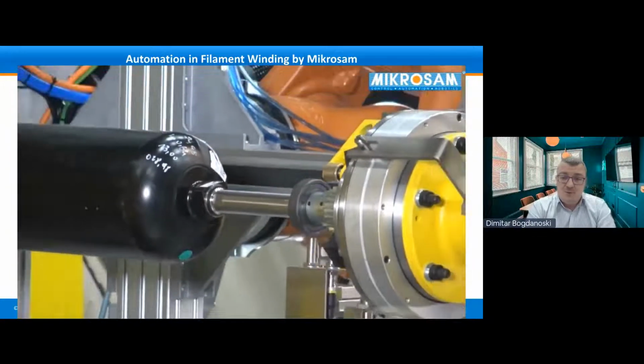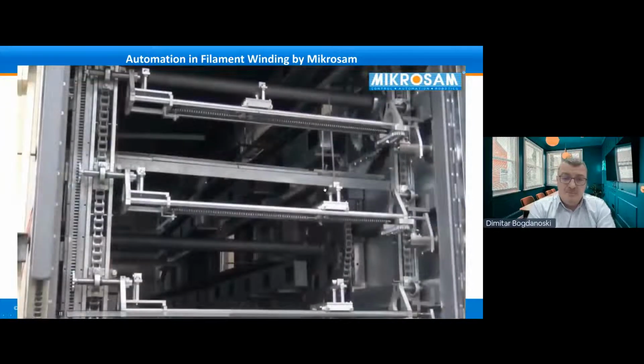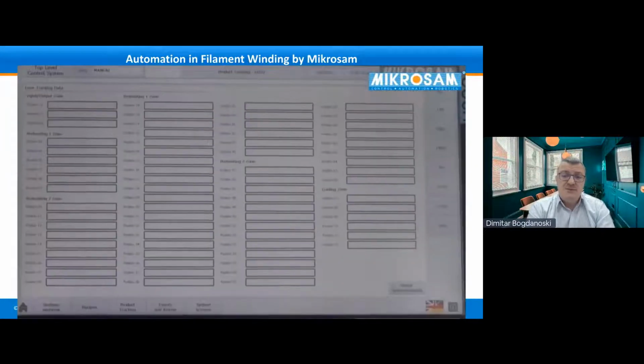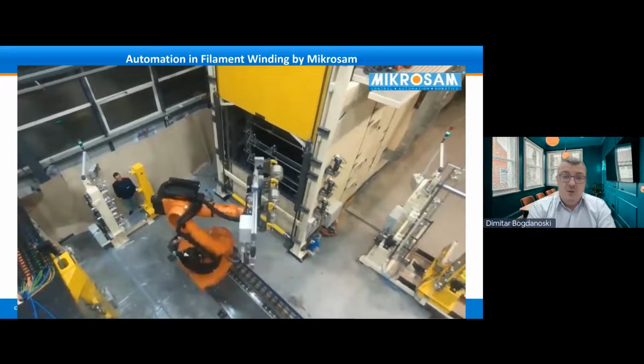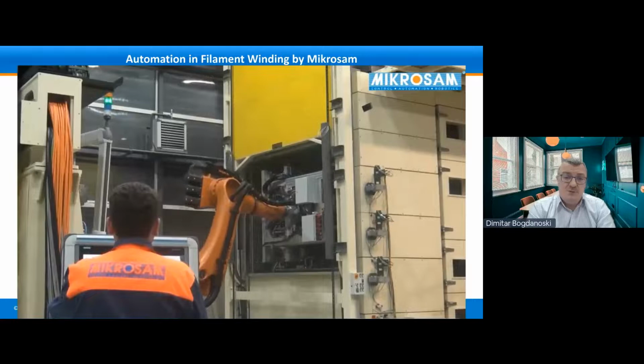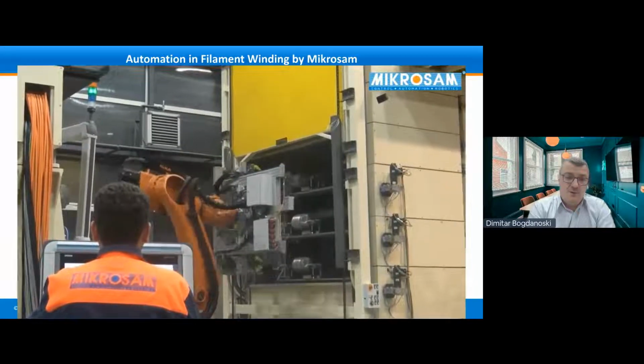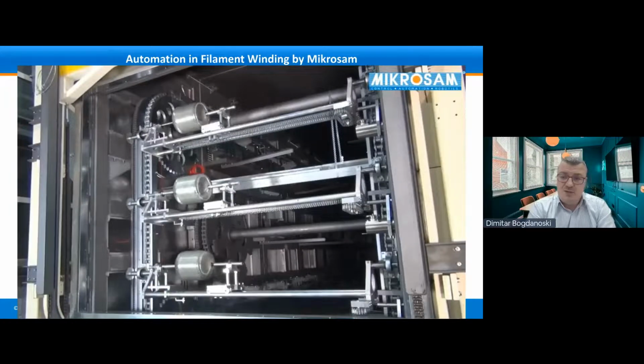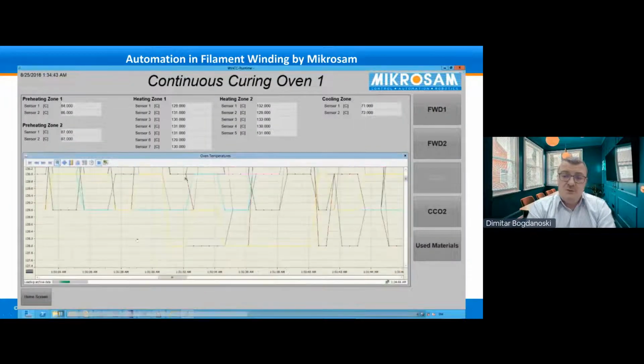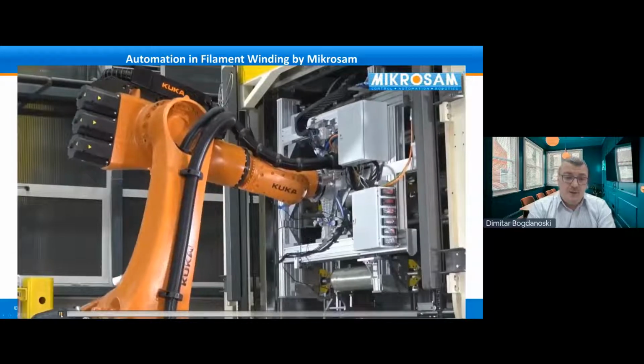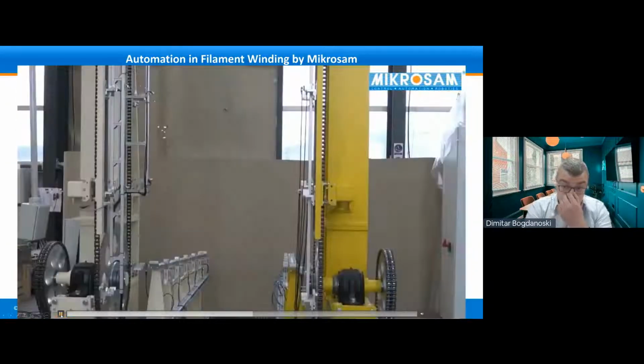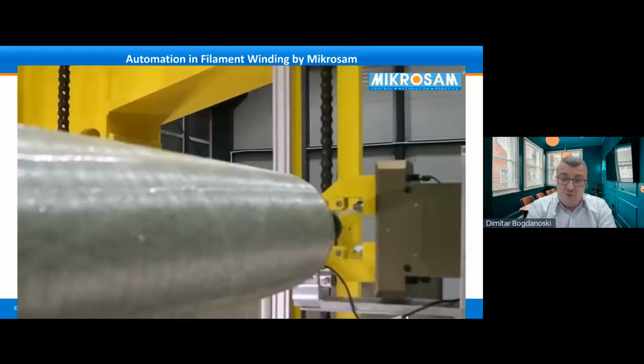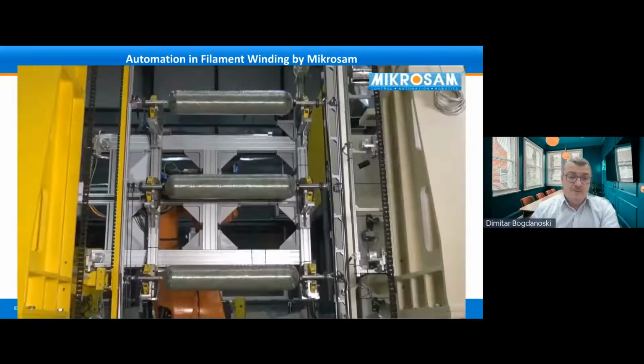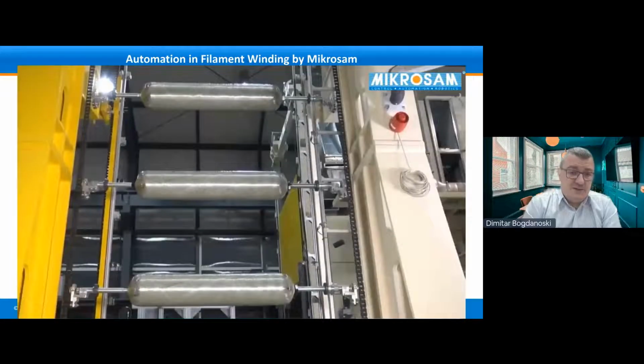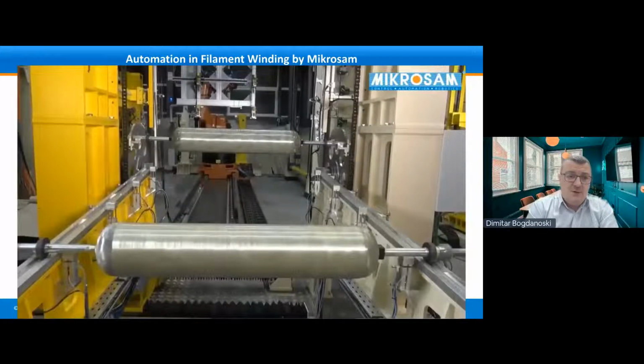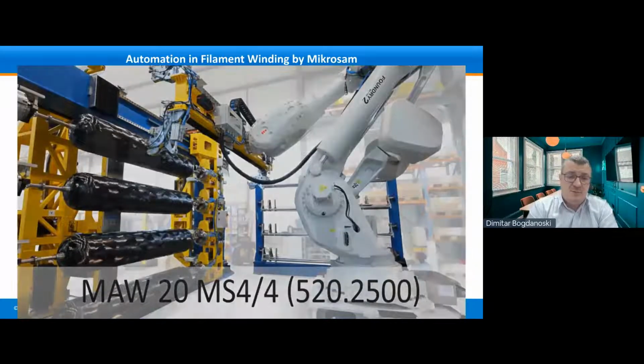Next phase of the production process is the curing oven. And the oven is designed based on the resin system used and required curing cycle. In the oven, we have a constant process of continuous rotation and translation, so that the resin does not drop down. And in the oven, we also continuously record the curing temperature. Final step of this production line after the curing oven is a drop-off station of finished cylinders. And after this station, the cylinders are taken over for the next phase of the production process.